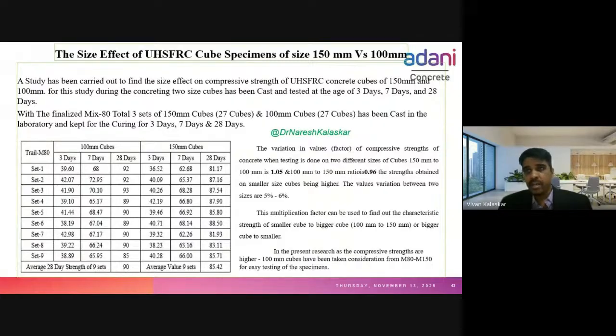So we have done one more study on this UHPC, because usually in southern India, I did my research in a university laboratory, where we had only a 3000 kN compressive testing machine. For testing M150 cubes, we need a minimum 5000 kN machine if you are casting 150 mm cubes. So that is the reason I did one more thing. I reduced the cube size. I casted 100 mm cubes and 150 mm cubes, and I took external lab support where a 5000 kN machine was there.